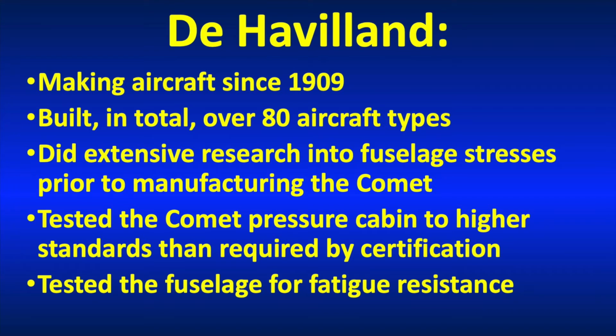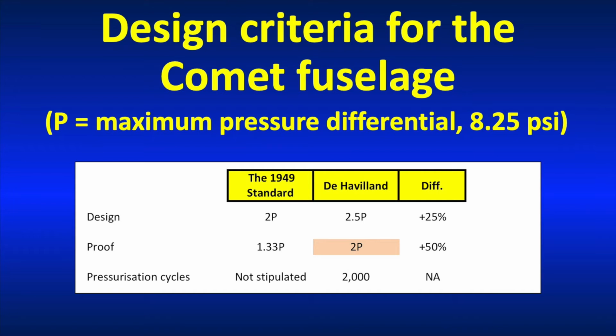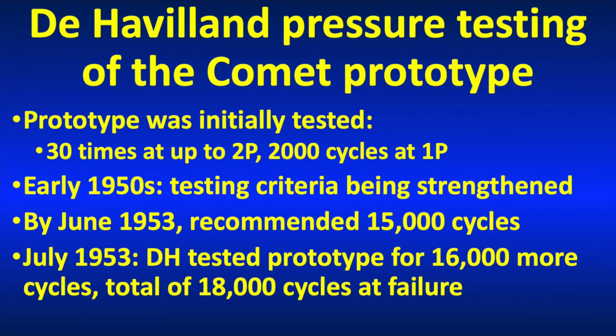So the standards in 1949 weren't particularly stringent because they were mainly intended for non-pressurised aircraft. So as you can see here, they did quite a bit more. They tested the Comet to higher standards than was required, and they tested it over 2,000 pressurisation cycles. But I've highlighted the 2P there because that was a cause of major problems. By the early 1950s, the standards for certification were really creeping up, and in particular there was an increasing understanding of the effects of fatigue and the potential risks.